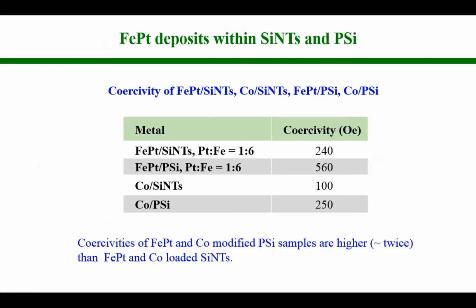So this comparison here shows data from silicon nanotubes and porous silicon (PSi) filled with iron platinum and filled with cobalt. And what we see is that in both cases, the coercivities for the porous silicon (PSi) composite are higher than for the silicon nanotube composite.